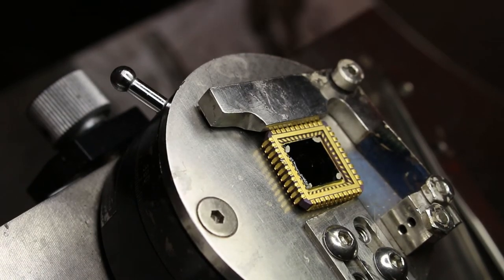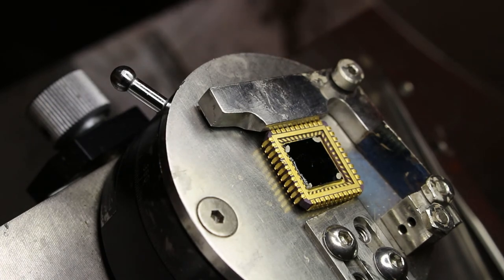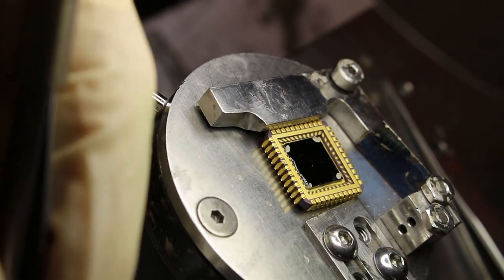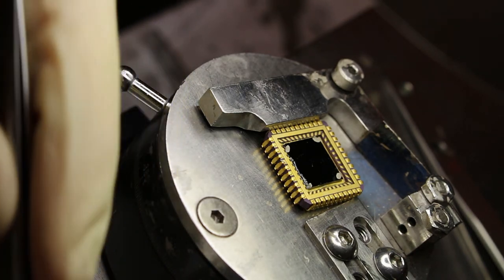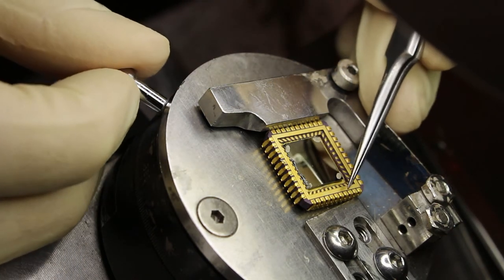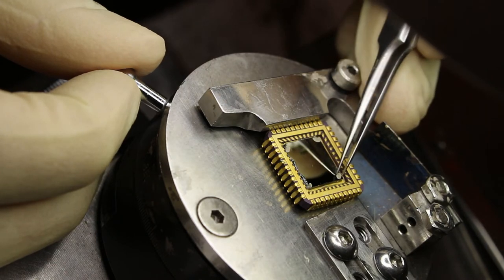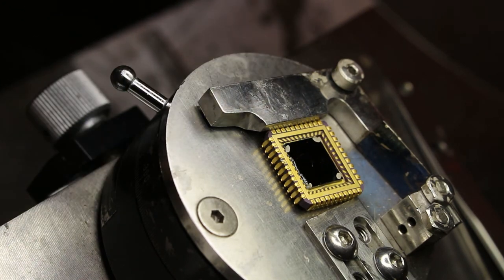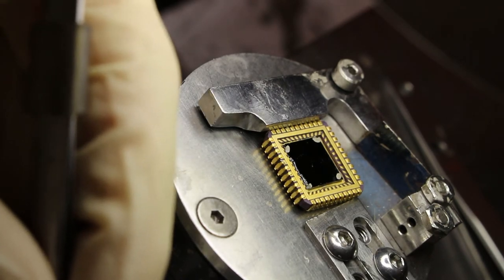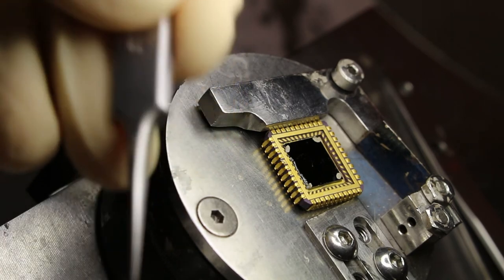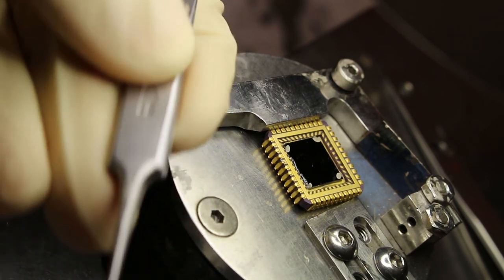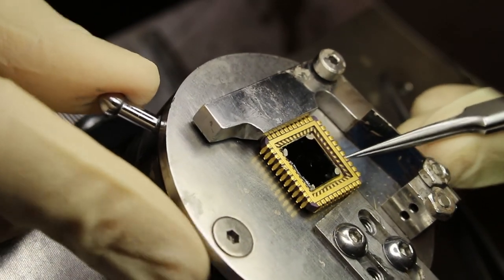Now unfortunately with this sample, this is all silver paint dots. So it's going to be a little bit trickier. I don't have the indium to press this wire into, but we'll see. We'll get it to work. I've already deposited these or put these silver paint contacts on the other day and let them dry. It might actually have been easier to leave them wet. So we'll see. Oh, I'm not going to use this wire. I don't know if you can see it in the video, but it actually has a little bend in it. I don't want that because those have a tendency to break. If there's a sharp crease in the gold wire, they have a tendency to break or just have not stable resistance, especially since we're going to be temperature cycling these down to two Kelvin multiple times. Not everything has the same thermal expansion coefficient.